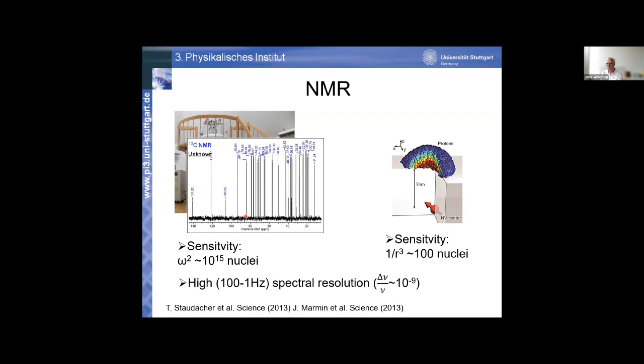Now, as a side remark, why do we have these multiple frequencies here? Well, these multiple frequencies come from the fact that the nucleus is seeing a chemical shift, and the chemical shift actually is a diamagnetic screening effect. The electronic wave function surrounding the nuclear spin is trying to diamagnetically shield the nuclear spins from the external magnetic field. Even though all of the orbitals are occupied, so you have pairs of electrons, no paramagnetism, you have a diamagnetism, and this diamagnetism in the molecule depends on the local electron density, which is unevenly distributed across the molecule. And so essentially what you measure here is local electron density, and this local electron density directly relates to the molecular wave function, and this directly gives you access to structure information. And there is rich structure information, that's what you see here.